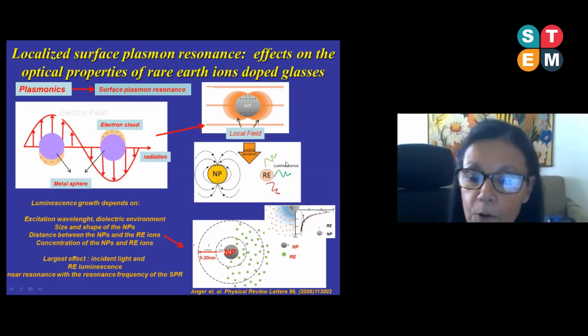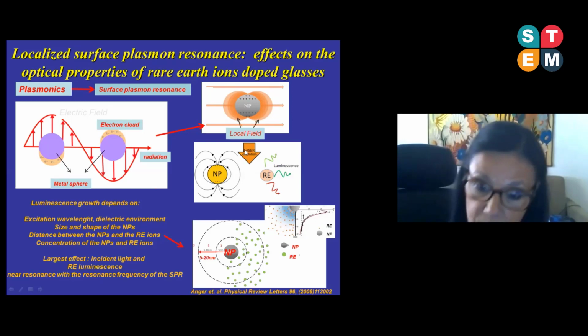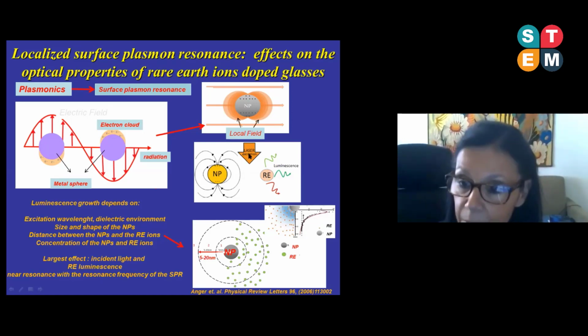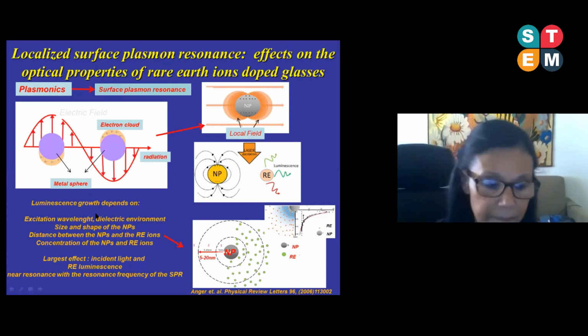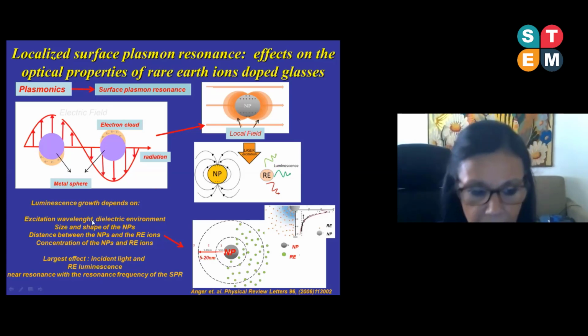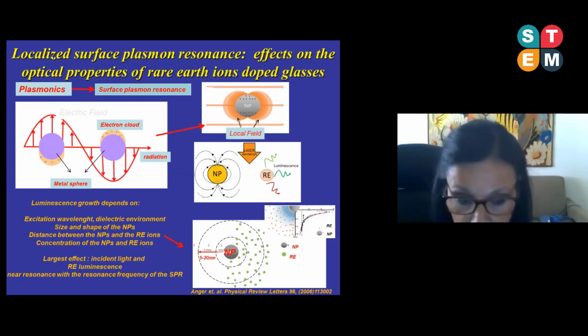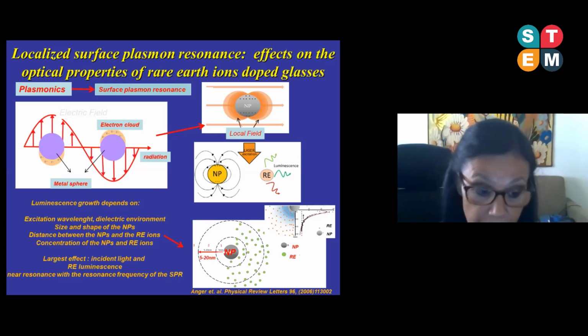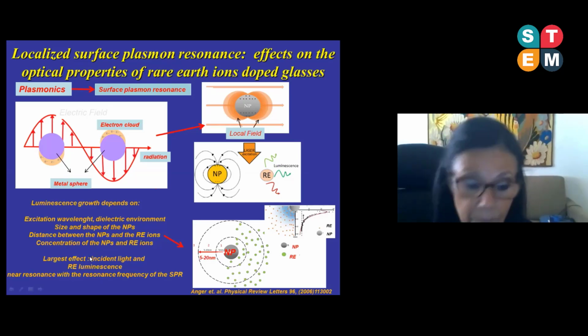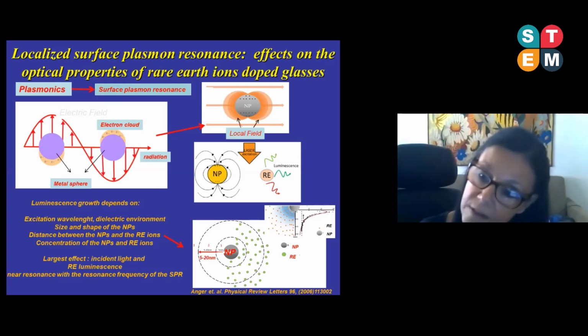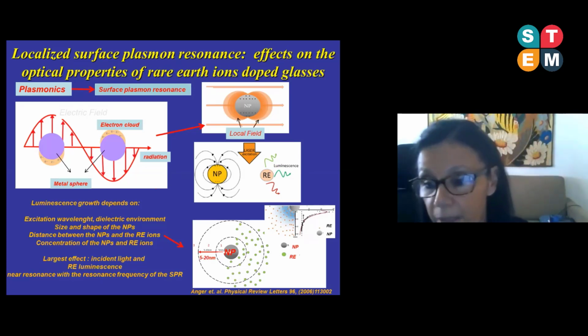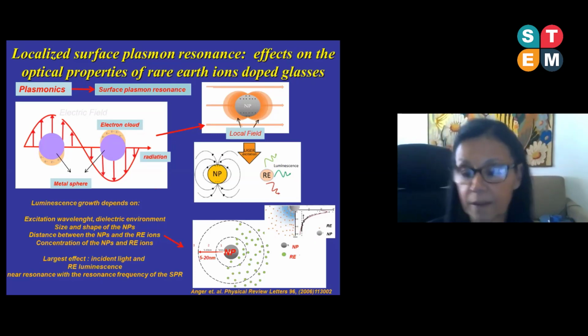When we approach the rare earth ion to this local field, the luminescence can be enhanced, and of course this growth depends on several parameters that are listed here. The excitation wavelength, the size and shape of the nanoparticles, the host, the distance between the nanoparticles and the rare earth ions, the concentration, and the largest effect, the largest enhancement takes place when both frequencies, the one of the incident light and the rare earth luminescence, approach the one of the surface plasmon resonance.